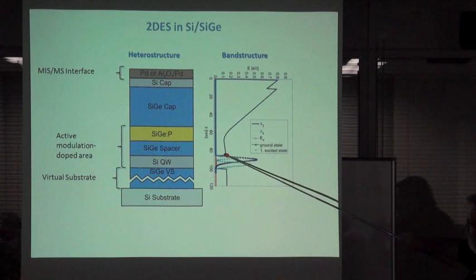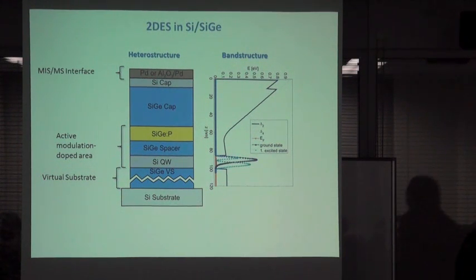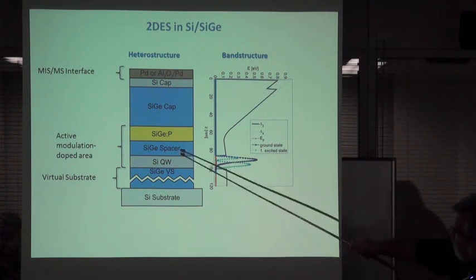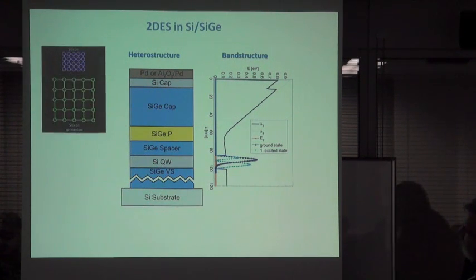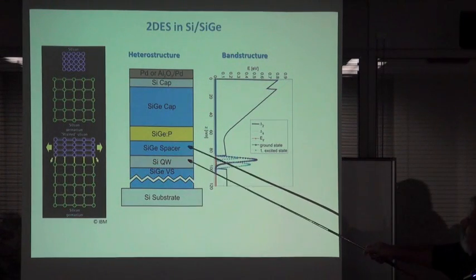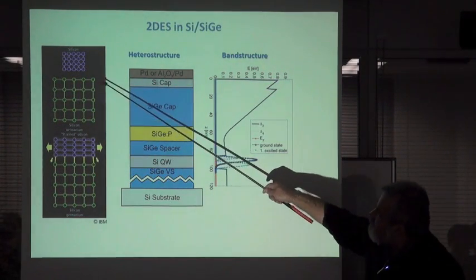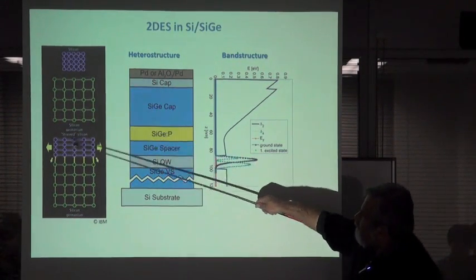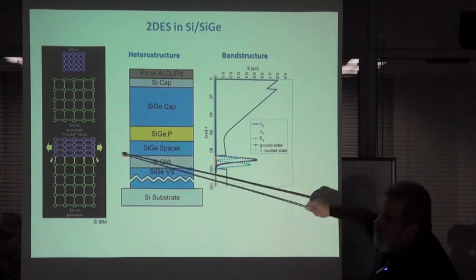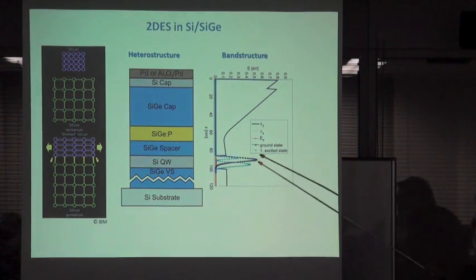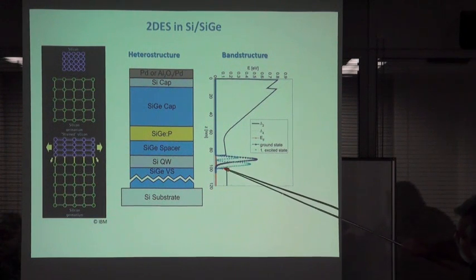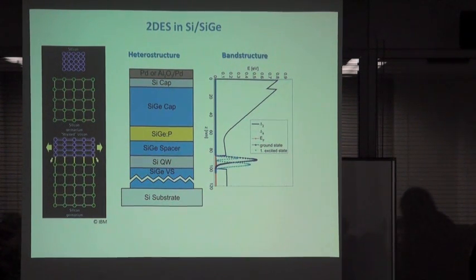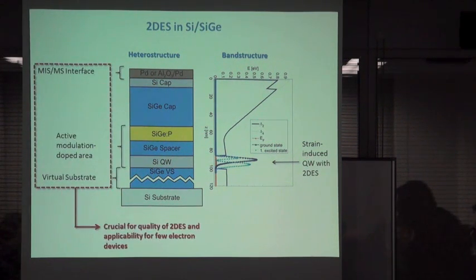This is a calculation of the ground state and first excited states in such a quantum well. So we have this active modulation doped area. Now typically this is shown schematically: you have this smaller lattice constant, you bring it to a larger lattice constant, and then you have tensile strain, and this makes the band structure like this, so that you have a potential well for the electrons here in the silicon. This is the strain-induced quantum well, which contains the two-dimensional electron gas.